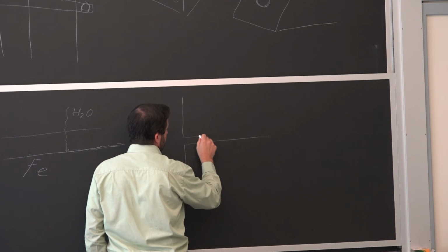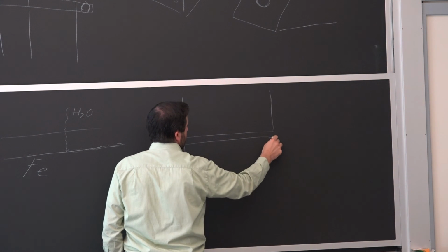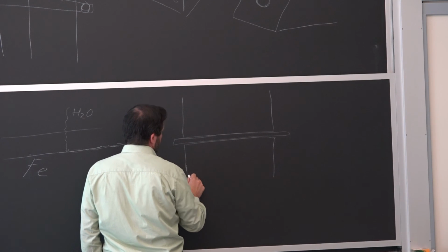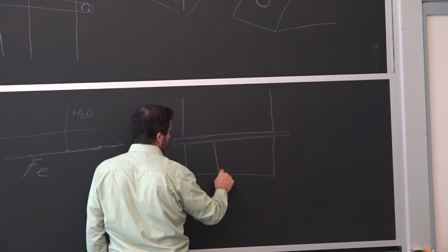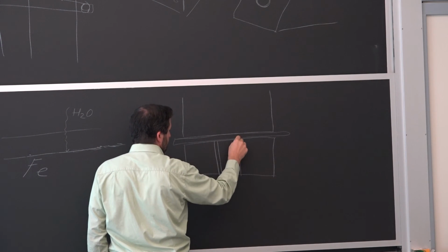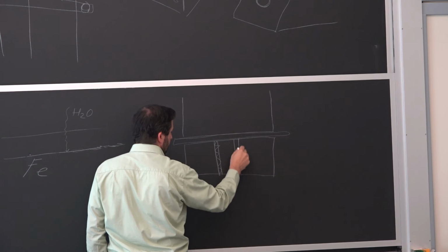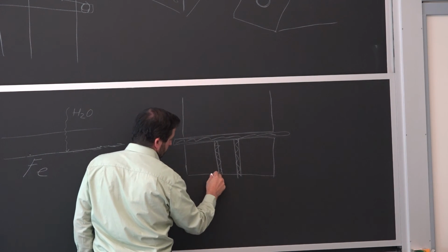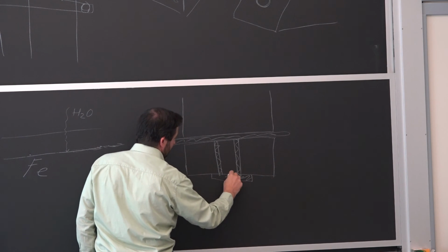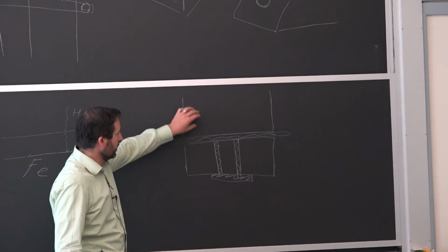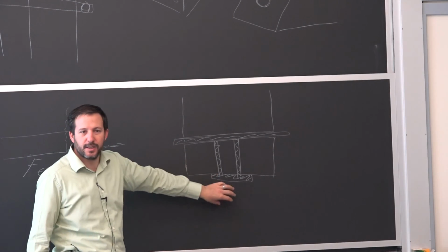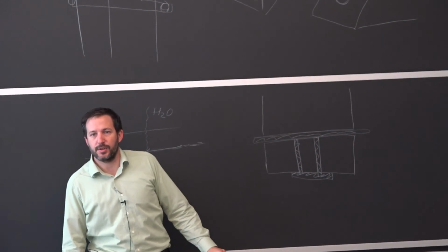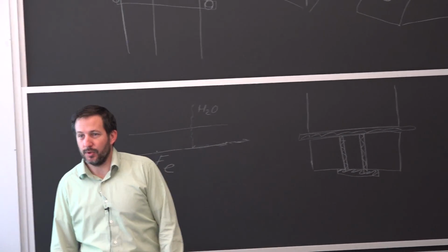So let's say I have two flanges coming together. I can put the dielectric here, and if I have bolts, what it means is I also need to put a sleeve here. So there's a dielectric sleeve. This is all dielectric, and then a dielectric washer. It's the only way, if I'm trying to connect material A to B, that I can do it without having a problem.